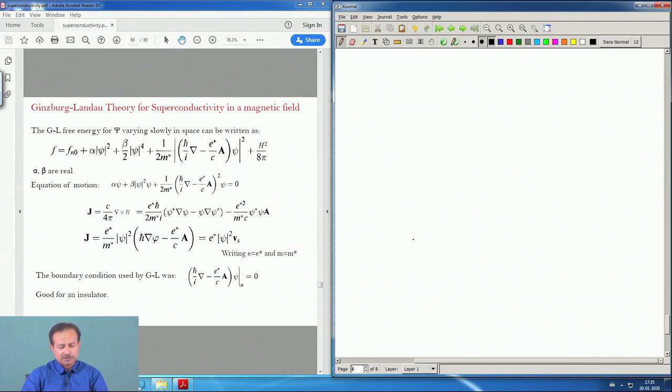There is a state possible where the magnetic field can penetrate a superconductor depending on the conditions that we will outline, and in that state superconductivity and magnetic flux inside the superconductor coexist in the sense that the flux actually penetrates in some tube-like structures which are called vortices, and the superconducting order parameter goes down to 0 at the core of these vortices, and in the rest of the situation outside this vortex, the superconductor remains a normal superconductor, just like the superconductor it was.